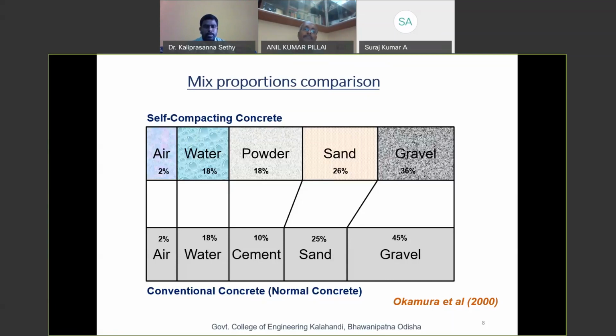And powder in the case of self-compacting concrete is mentioned as powder, whereas in normal concrete it is mentioned as cement, because we know it is a mixture of cement, sand, coarse aggregate, and water. But in self-compacting concrete, we are increasing the powder content to achieve more paste. To achieve more paste, we have to increase the amount of cement. But if we increase the amount of cement, we may get a rich mix and increase the cost of the concrete. That's why we try to use waste material, industrial slag, for the development purpose. And talking about sand, it is almost similar.